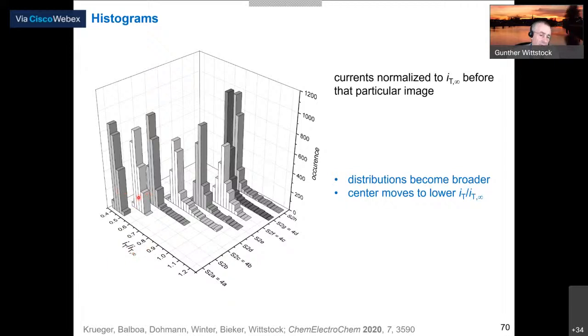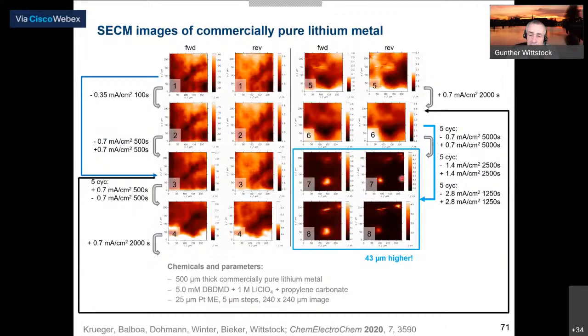So we see that the normalized current distribution gets broader as the experiment proceeds. So we get more variation of reaction rate over the surface. And it also gets lower because we probably form a solid electrolyte interface of higher thickness. That's the first observation. The second observation can be seen when we go to higher current densities, which are too high. Then we see that the surface really changes and a new area pops up with high currents. So we then concentrated on that.